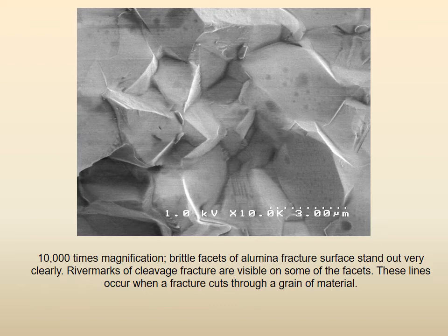So at least you see this is exactly on the grain boundaries. This is dimples all over, and here there are big flat surfaces. And whenever there are river patterns, oh yes, these river patterns are there, so this is typical cleavage, right? So at least some basics.